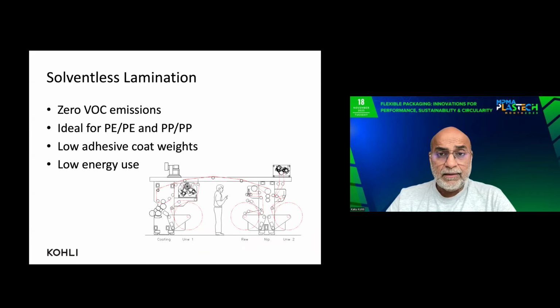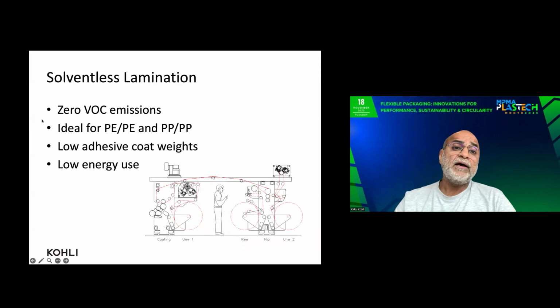Let's take a look at a typical laminator machine, a solventless laminator, where we have the unwinder, corona treating, coating assembly, then the lamination nip, the secondary unwinder, the second corona treatment, and the rewinder. The advantages are zero VOC emissions. It's ideal for PE laminate or PP laminate structure. Such machines can offer a very low adhesive coat weight and very low energy consumption.